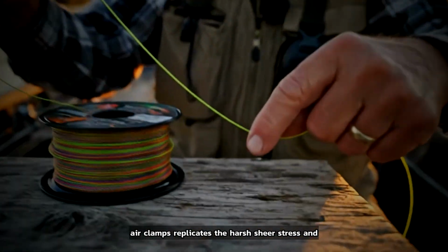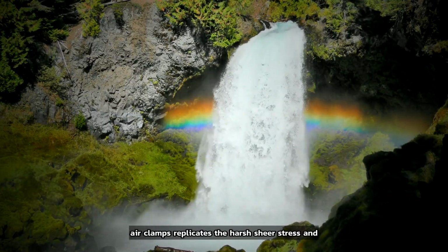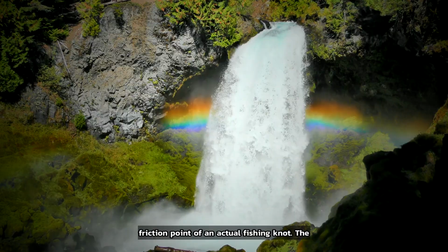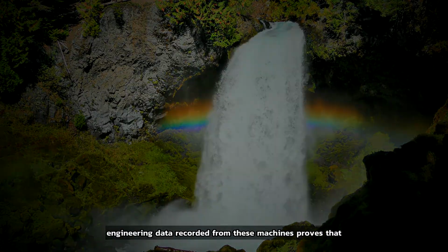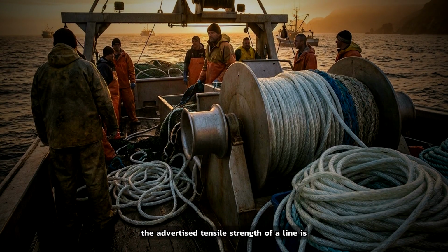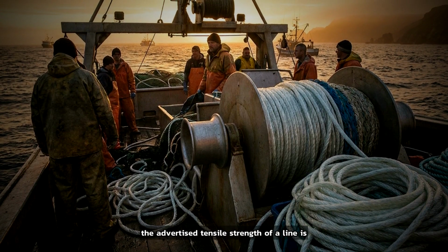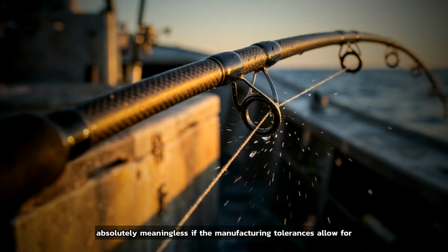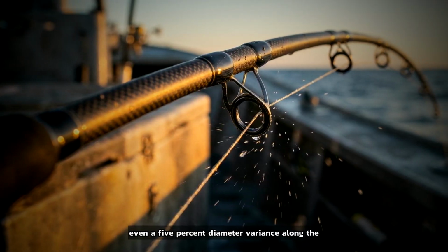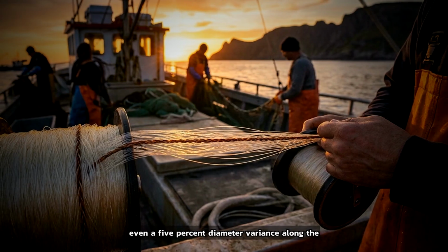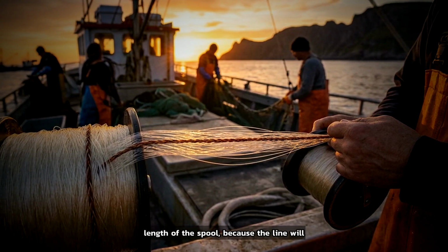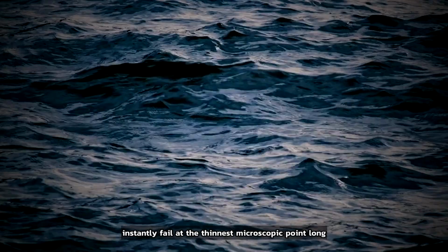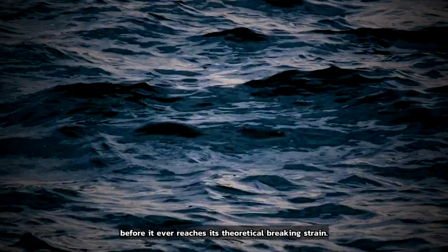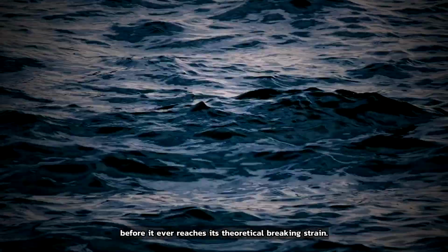Testing the line with air clamps replicates the harsh shear stress and friction point of an actual fishing knot. The engineering data recorded from these machines proves that the advertised tensile strength of a line is absolutely meaningless if the manufacturing tolerances allow for even a 5% diameter variance along the length of the spool, because the line will instantly fail at the thinnest microscopic point, long before it ever reaches its theoretical breaking strain.